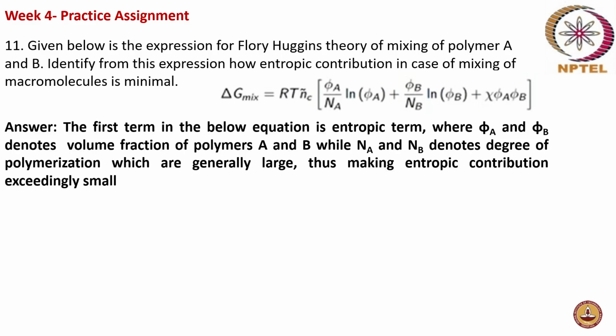It's nothing but your Na and Nb. These denote the degree of polymerization. So the degree of polymerization will be high, right? And as you said, phi A and phi B are volume fractions, so the logarithm of phi A and phi B will be very small values. The combination of these two makes the entropic contribution very small. You're able to figure out this denominator value is large. That means if the denominator is large, the overall value will be very small, right?